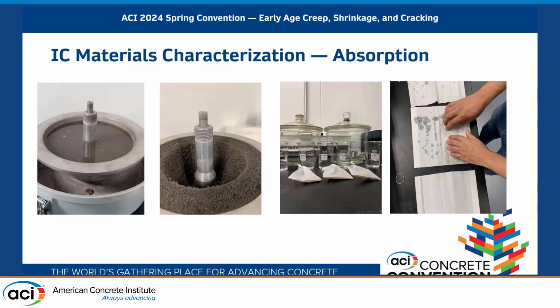Whether, in the case, for example, of recycled concrete, we found that the absorption capacities and the desorption characteristics of different sources were too widely different. Even from the same source, they would change from load to load, to the point where it was very unreliable in terms of how it was going to perform.